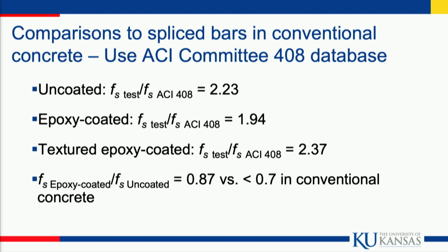Also, if you take a look at the ratio between the bar stress in the epoxy-coated bars and the stress you can mobilize at the same compressive strength in uncoated bars, the ratio in our test came out to be 0.87. That compares to numbers less than 0.7 in conventional concrete, so much less impact of the epoxy coating.